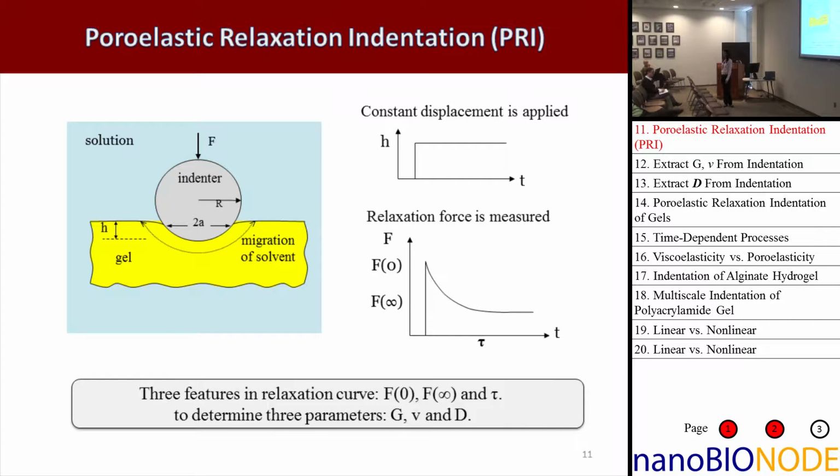Well, how do we characterize this material? We first put the gel into solution until it is fully swollen. Then we press the indenter into the gel to a certain depth and measure the relaxation force. There is a very important theoretical point for us to do relaxation test rather than creep test. I will come back to this point later.